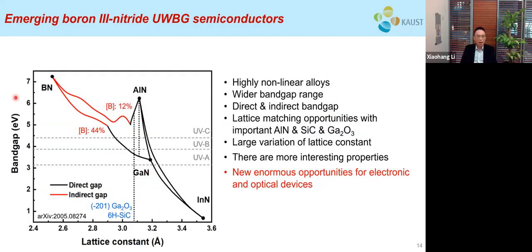So here shows the bandgap versus lattice constant of the boron aluminum nitride and boron gallium nitride, along with the more conventional III-nitride materials. As opposed to the more conventional materials, they are highly nonlinear, as you can see from those curves here. They also have a wider bandgap range and a direct to indirect bandgap transition. And they can form lattice matching opportunities with technically important aluminum nitride, silicon carbide, and gallium oxide substrates.